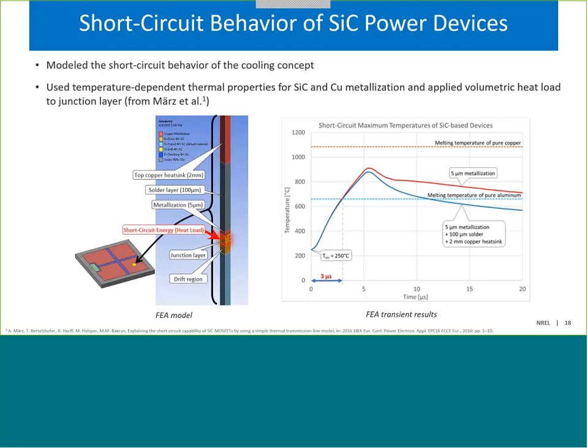We are predicting slightly lower temperatures for the current design, but the results are fairly negligible. And likely, in reality, delaying the temperature rise during a short circuit fault condition would require modifications within the device, and changing the package around the device likely has minimal effects, as we are seeing here. But it was a good experiment just to see what the effect of this cooling strategy would be on the short circuit fault condition.